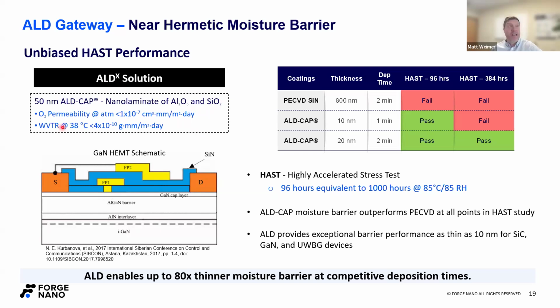So, I put some oxygen permeability and water vapor transport rates just as examples. But one of the things I will mention, and it's a question I get a lot when we talk to people, is, well, why can't we just do a single layer of aluminum oxide? Typically, when you compare a film, let's say 50 nanometers, the same thickness of aluminum oxide versus a nanolaminate that, let's say, is a ratio of 9 to 1, the permeability of oxygen and the water vapor transport rate decrease by an order of magnitude or 2. So depends on the application is the real answer. Sometimes a single bulk layer of alumina, that's enough. But for a lot of, say, telecom applications or even data center applications, you just need better protection. So that's the first point on this slide.